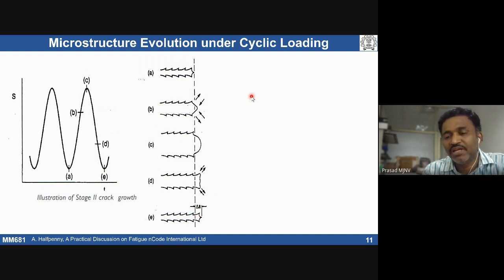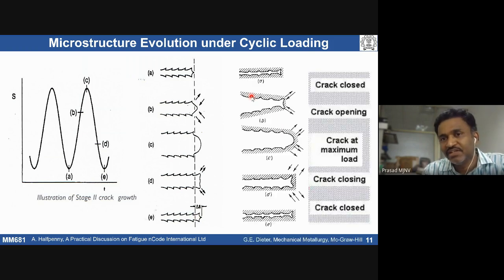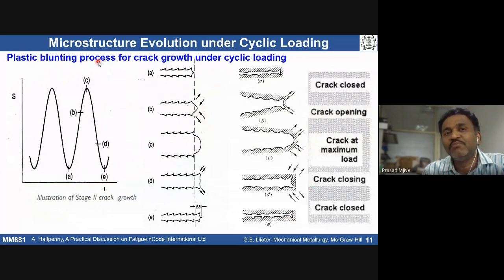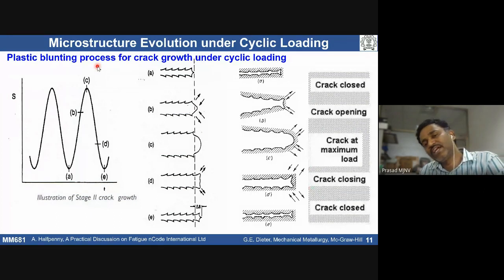So one can summarize it like this. Usually the crack opens, then the crack is at maximum load, and then the crack is going to get closed. Finally the crack has been closed, but at the same time the crack front has moved, extended a certain length. This whole process is called the plastic blunting process for crack growth. The mechanism that has been proposed is basically called the plastic blunting process for crack growth under cyclic loading conditions.